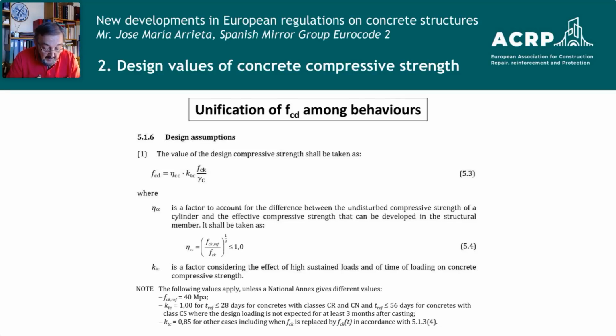When there is reinforcement, we have a brittleness because of the possible splitting of the concrete. So this coefficient eta_cc is the conversion from undisturbed to disturbed, to real concrete in our structure. The expression is there, the quotient between the resistance of reference and the characteristic strength of the test, and with that we unify this strength among all the behaviors.